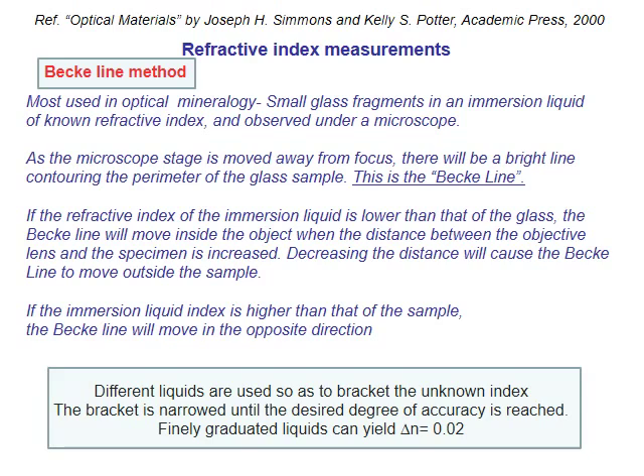The Becke line method is most used in optical mineralogy. Small glass fragments in an immersion liquid of known refractive index are observed under a microscope. As the microscope stage is moved away from focus, there will be a bright line contouring the perimeter of the glass sample. This is the Becke line.